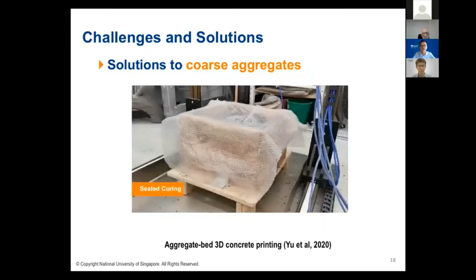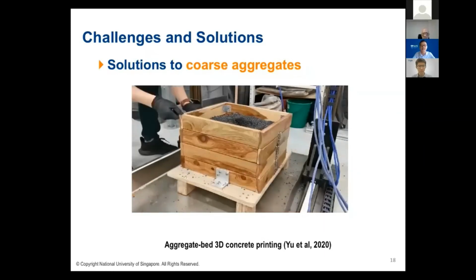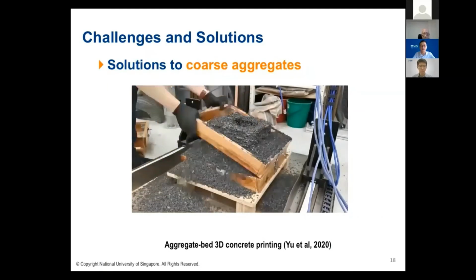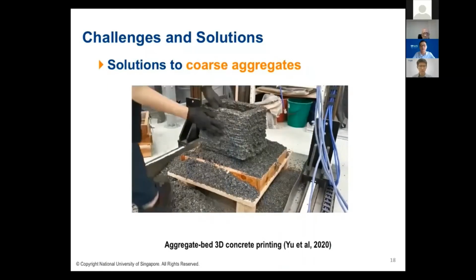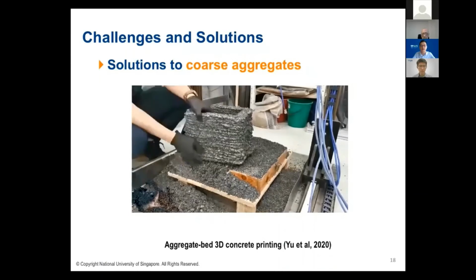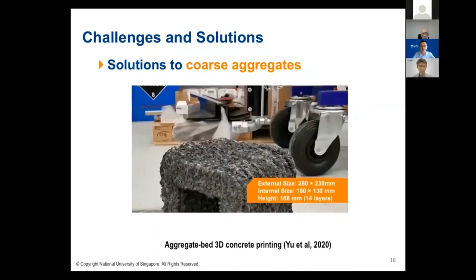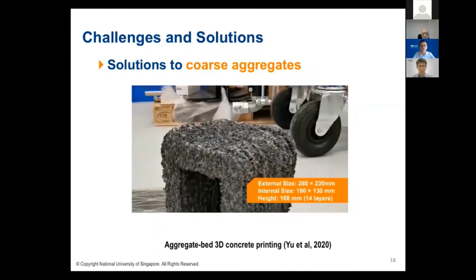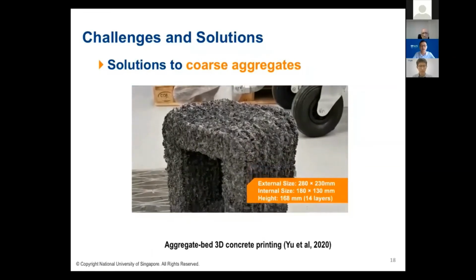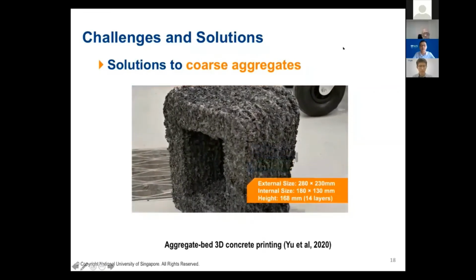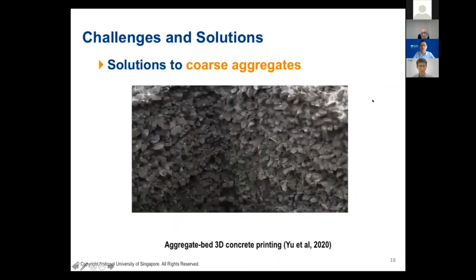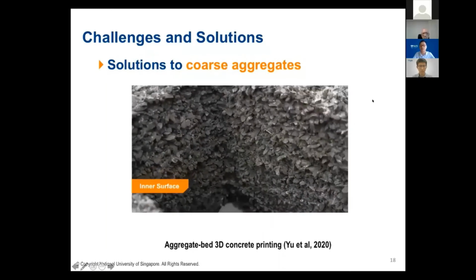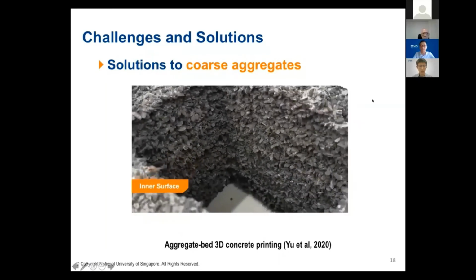So we leave everything in the box for 24 hours. Then on the next day, we remove everything. And the product is here. And the unbounded aggregate can be recycled. So this is the final product. You can see the coarse aggregate can be successfully integrated during the printing process.